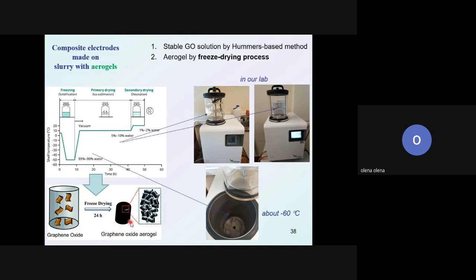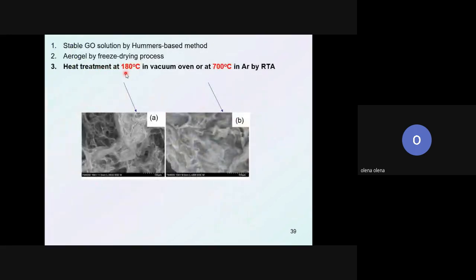And we have a cylindrical shape because we use a plastic cup. But you can see here it can also be another shape, rectangular, or whatever you want. To obtain reduced graphene oxide, we make a reduction heat treatment at 180 in a vacuum oven and at 700 in argon by rapid thermal annealing. Here is 180 and here 700. It is visible that reduced graphene oxide obtained at a higher temperature looks more dense, let's say.